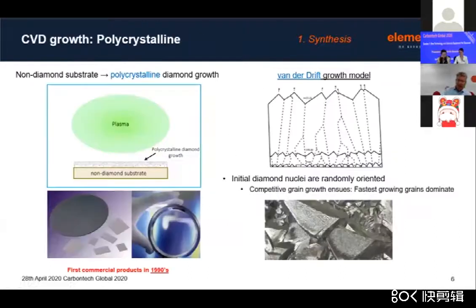And then effectively, there are two materials that we can develop. In the early 90s, people developed polycrystalline diamond, where you've actually got these randomly orientated crystals that then get a preferred orientation, and they start to grow up into the direction, and they become columnar. And it's very important that after some time of growth, these columnar grains get pretty much parallel, and the grain sizes don't get any larger. At the beginning of growth, you see rapid grain growth, but after some time, you tend to slow down and see these crystals grow up.